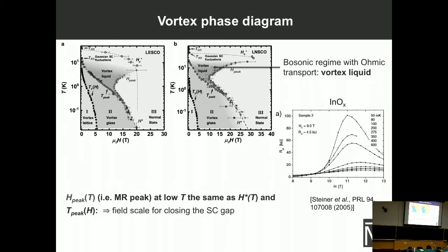So that means also that here, where we still see this peak, we have access to the bosonic regime where transport is ohmic. So we identify this with the vortex liquid. So this is consistent with the general picture that I described at the beginning. At high enough temperatures, you have a vortex liquid, you cool the system down, and vortices slow down and start to exhibit some kind of glassy behavior.